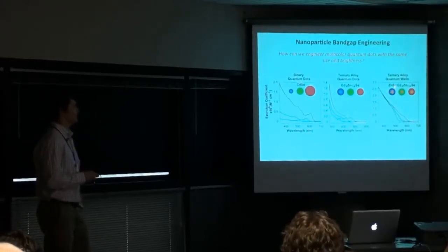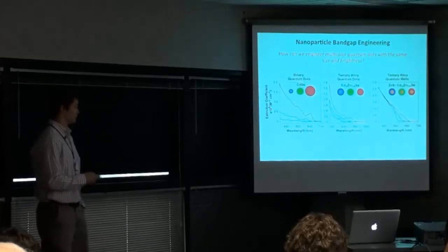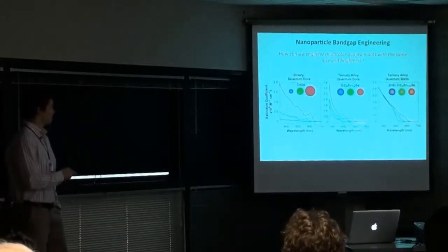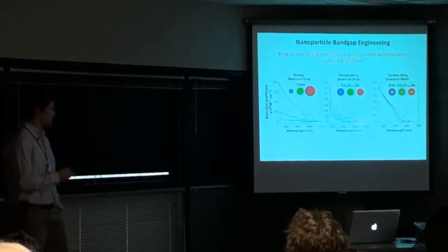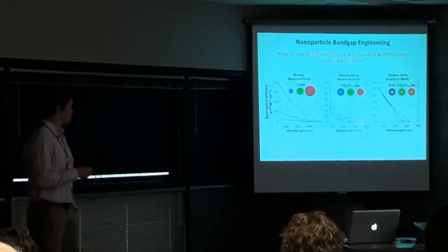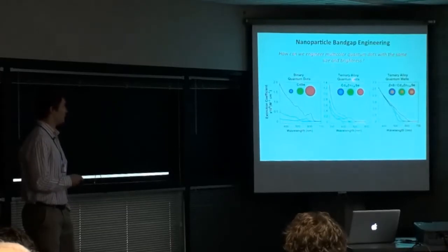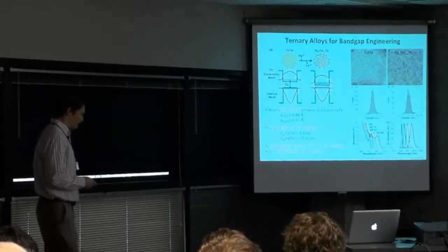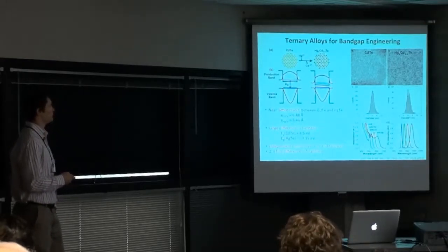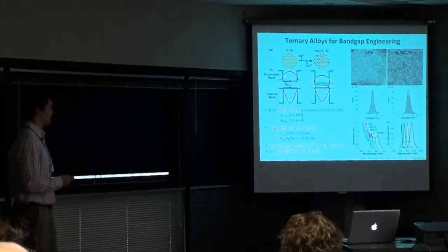We can further normalize these with a new material we developed called a ternary alloy quantum well, in which we take out the center of these particles and have only one-dimensional confinement. These are fantastic, however they have to be very large — the core is at least four nanometers, the shell is another two nanometers, and an additional insulating shell makes them very large. Currently we're focusing on ternary alloy quantum dots. The challenge is that when you synthesize quantum dots and add a third material, you add another level of compositional inhomogeneity. We've developed a way to take homogeneous binary nanoparticles and homogeneously alloy them in a second step, based on cation exchange.